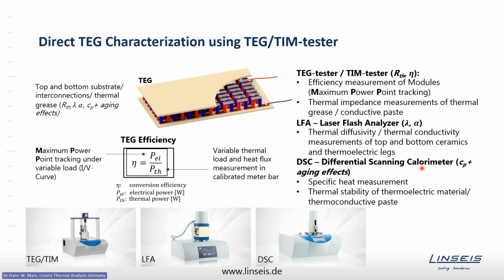And the differential scanning calorimeter is used to measure the heat capacity, which is needed to calculate the thermal conductivity from the thermal diffusivity. So for a complete measurement by the laser flash analyzers. And a DSC may also be used to characterize the thermal stability of these thermoelectric materials, but also of other chemicals like the thermoconductive pastes used to build a thermoelectric generator.